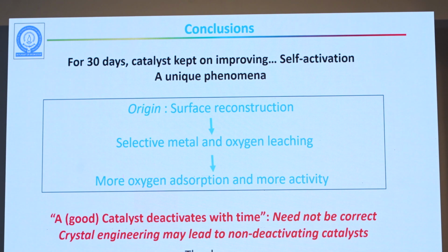So, what we saw is that for 30 days of catalysis, the catalyst keeps improving. This is what we call self-activation. We find that it's probably the only example where you see a catalyst which is already very good, but keeps improving with time. And the origin is surface reconstruction, selective metal leaching, and oxygen leaching. Therefore, you have more oxygen absorption and more reactivity. So, we started with this question: does a good catalyst necessarily go bad with time? But here we see that actually it improves with time. Thank you. I hope you all agree with me.